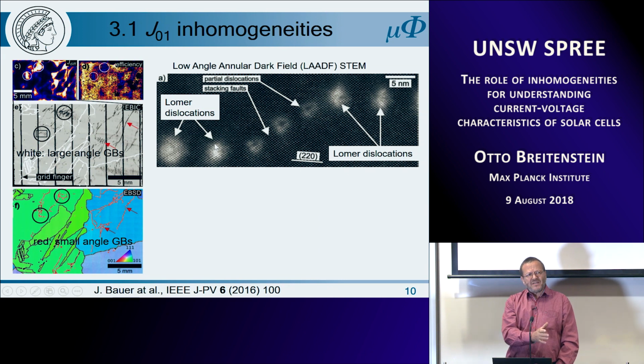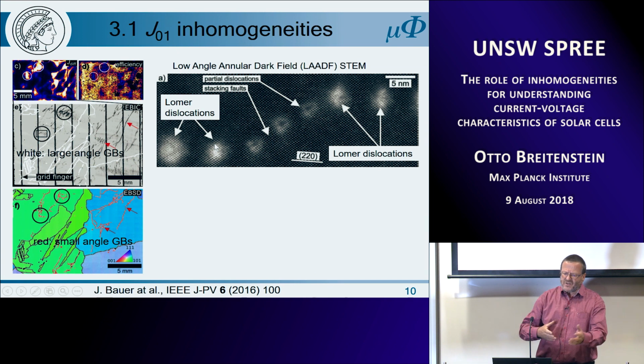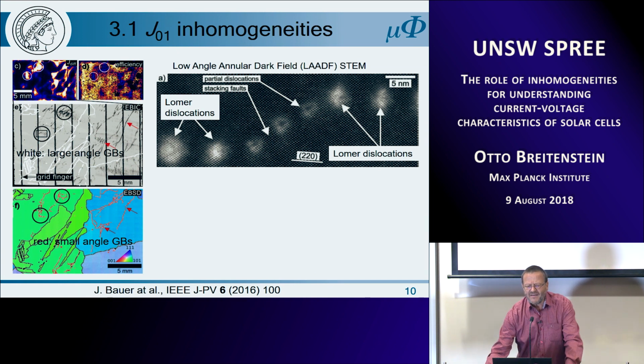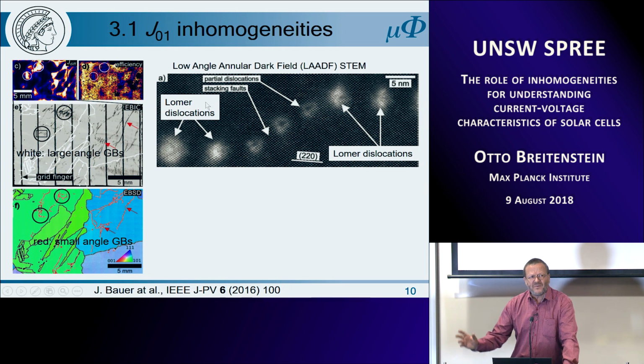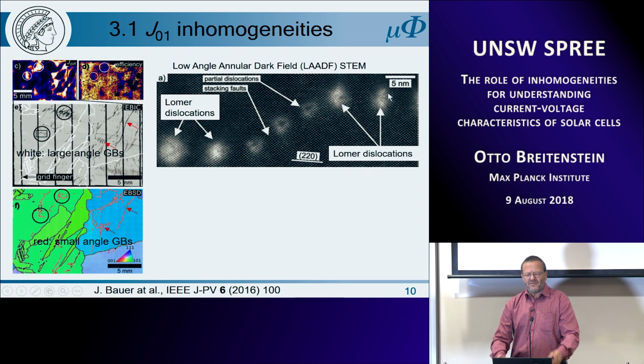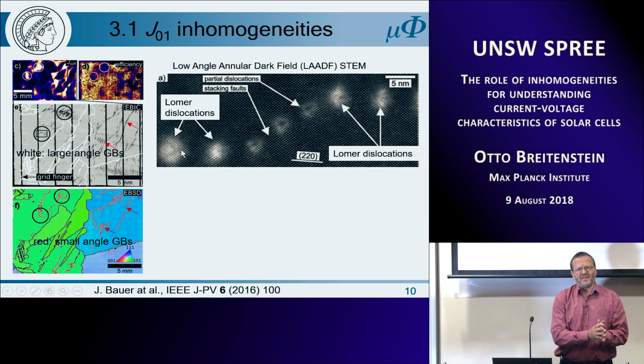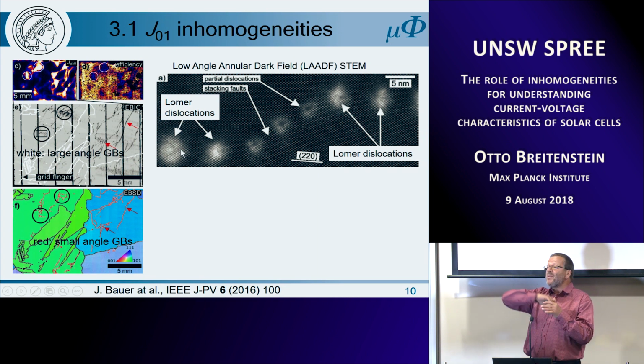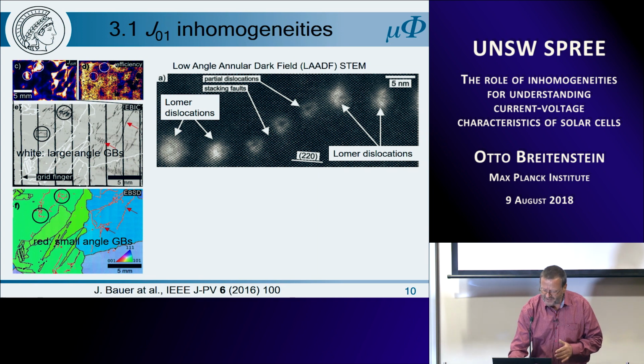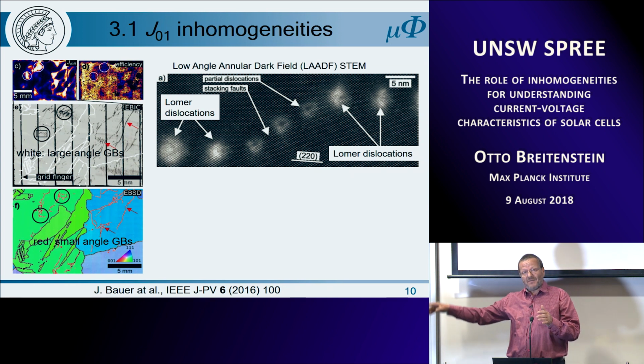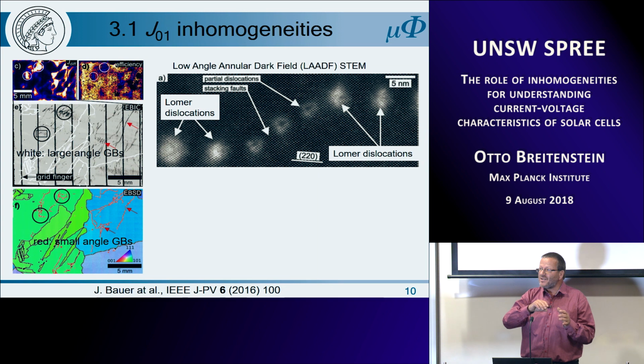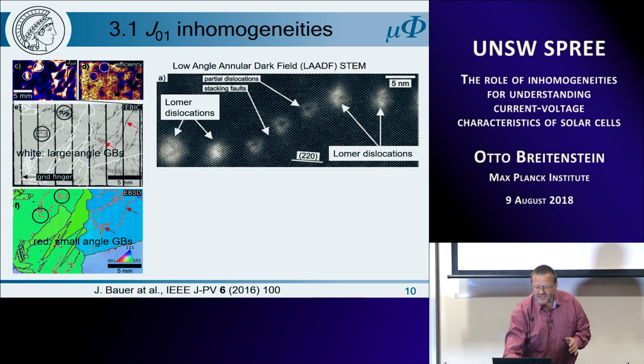And if they have a certain Burgers vector and a certain orientation, then they are so-called Lomer dislocations. In the paper, we have described exactly what this is. So these are Lomer dislocations, and these are other. And the ratio of Lomer dislocations to the other dislocations depends on the orientation of the grain boundary. And these were bent grain boundaries, so they did not have the same EBIC contrast and recombination contrast in each position.